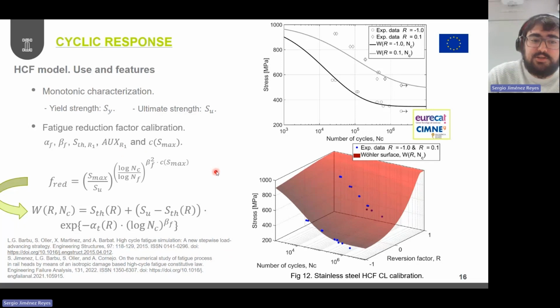And the good news is that this function can be connected somehow with the SN information, that is the typical information that is reported experimentally for characterizing the high cycle fatigue response of a material. So based on this connection between these two pieces of information in terms of fatigue, we also built a mathematical expression to capture this SN information through this Wöhler surface, which is based on exactly the same parameters that we used to define the fatigue reduction factor. Meaning that by calibrating this expression here, based on experimental data, we are automatically also characterizing the response of the constitutive law in terms of the fatigue reduction factor. And you can find more details about all these ideas in these two papers.